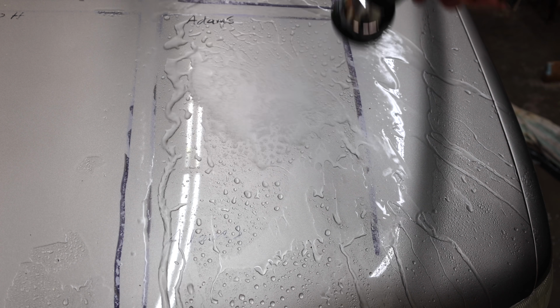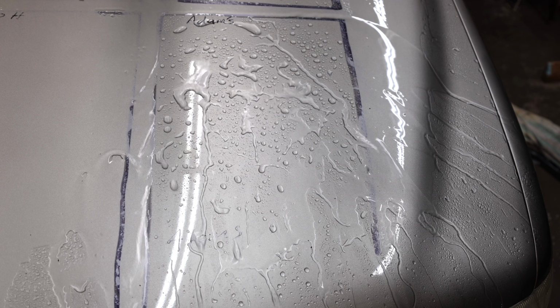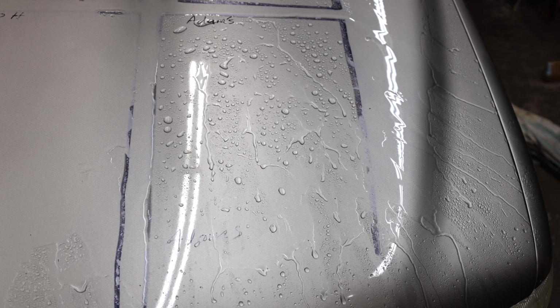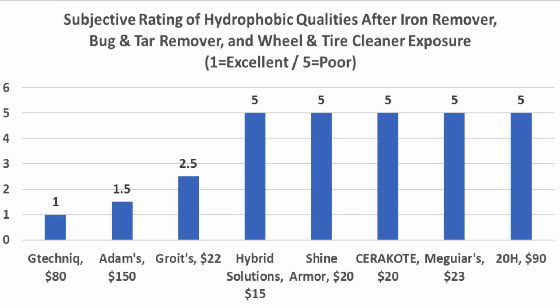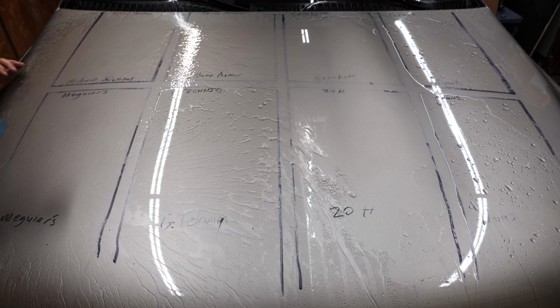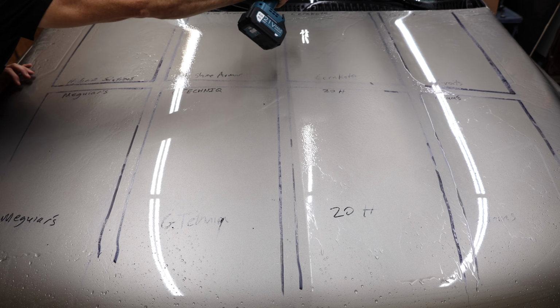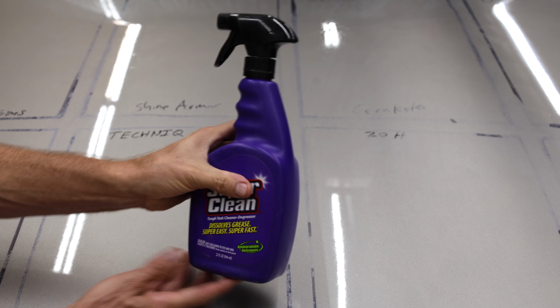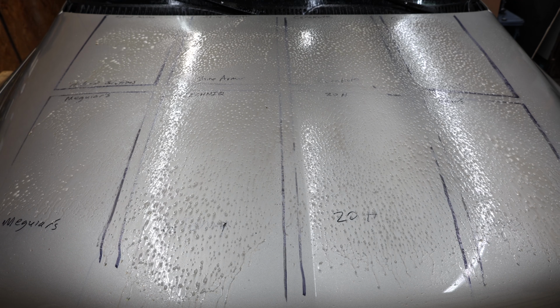And the Adams continues to impress just like the Gtechniq. The water is beading up, but the Gtechniq seems to be holding up just a little bit better. So after the strip wash, iron remover, bug and tar remover, and now the wheel and tire cleaner, the Gtechniq is still holding up the best. The Adams is holding on to a close second place position and Griot is in third. In the final test, let's see which ceramic coating can hold up the best to the winner of the degreaser review.